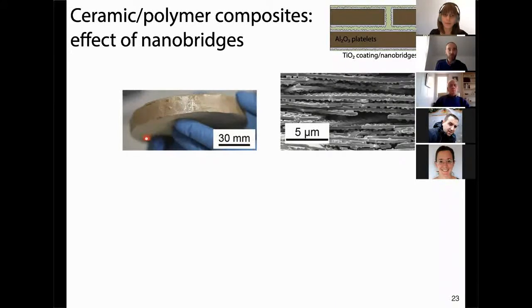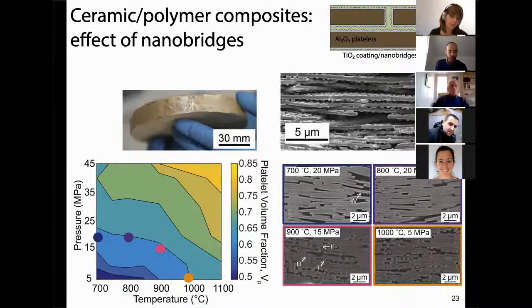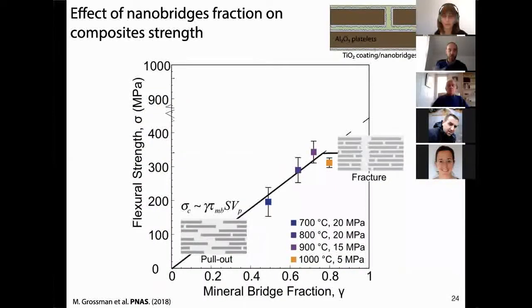And so first we upscale the size of the sample we could make. But we also changed the processing parameters, in terms of temperature and pressure. And we drew a map of the density we obtain for these different compositions. Now we can select a path where we are sure we have exactly the same density of material, so the same amount of mineral in our composite at the end. But because we change the temperature, we also change the volume fraction of these bridges, independently of the density.